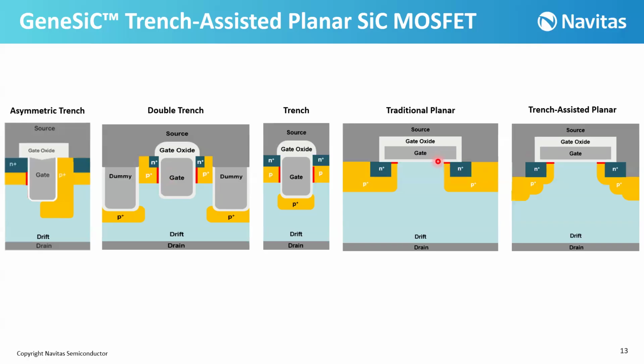So as I mentioned, the gate planars are more robust compared to the electric field protection. So the trench-assisted planar is a gate planar. So we have the channels at the surface, N plus, P well, and then we have the channel and drift, substrate and drain. But we have also a very shallow trench on the source area here. And in this shallow trench area, after that, we can have the P plus implantations. And by this, we are making other steps, or extra steps, of the P plus implantations. What is the reason for this? By these extra steps, or multi-step P plus implantations, we have a better protection of the gate oxide here. So obviously the gate oxide here sees a lower electric field compared to the traditional planar.